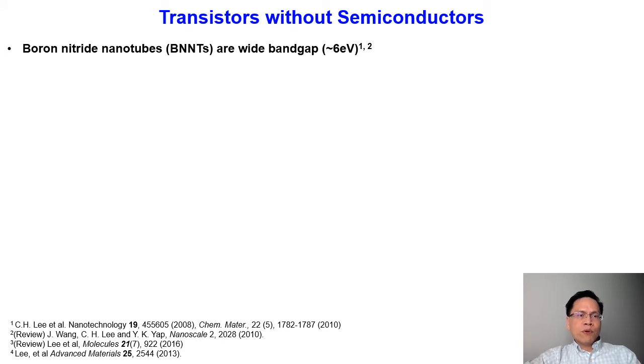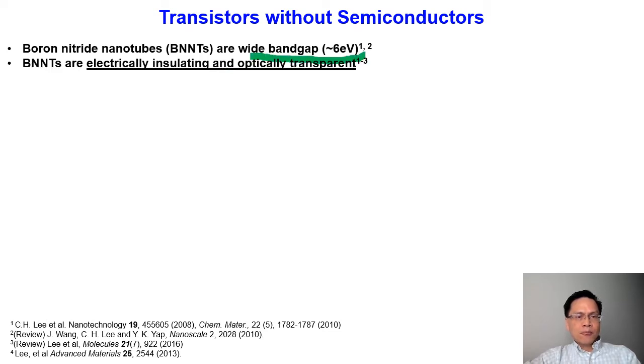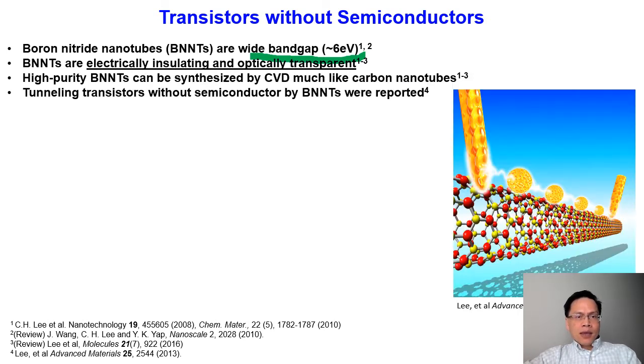What we have reported is that we use boron nitride nanotubes which have a bandgap of 6 electron volts, and of course they are always electrically insulating. We are depositing gold nanoparticles on the surface of boron nitride nanotubes, and then we are trying to probe using two pieces of STM probe on the electronic transport nature across the surface of these boron nitride nanotubes.